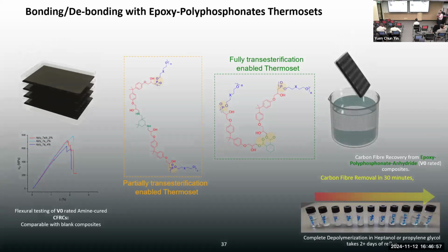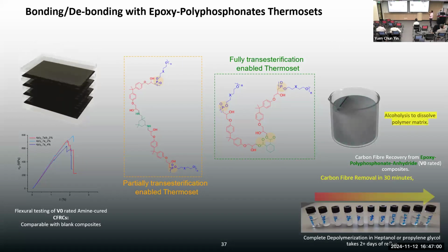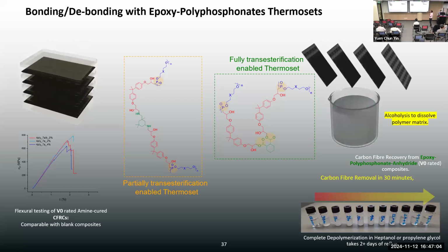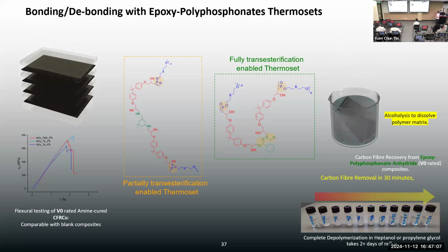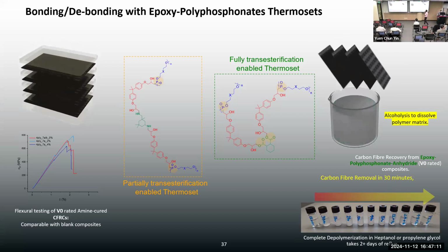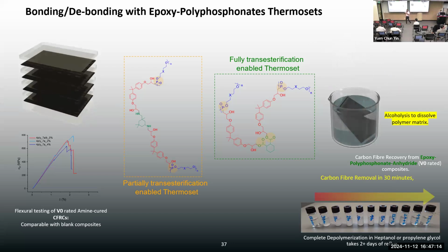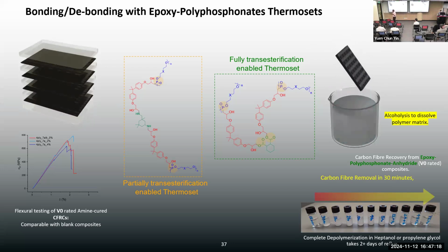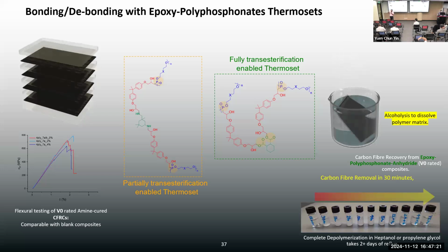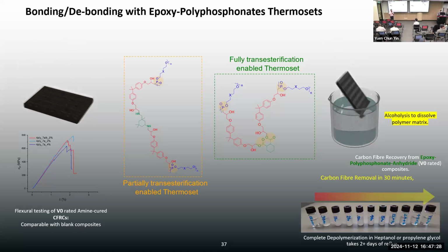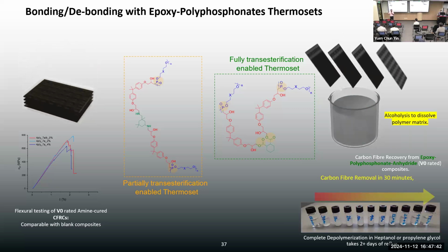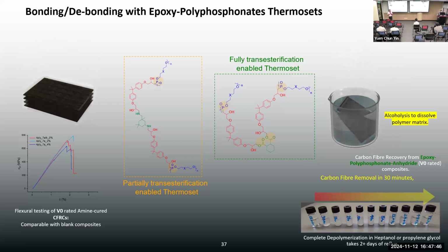Going forward, what else can we do with this? These resins, I showed you, can be used to make fiber reinforced composites. In this case, this is a carbon fiber reinforced composite. Normally, you impregnate each layer of glass or carbon fiber with this resin, and then you stack them on top of each other and press them into a composite. That's how you make composites. However, at end of life, carbon fabrics are pretty expensive. It would be nice to recover them. The price of a carbon fabric could go up to $200 per kilo. So imagine you want to recover this precious raw material.